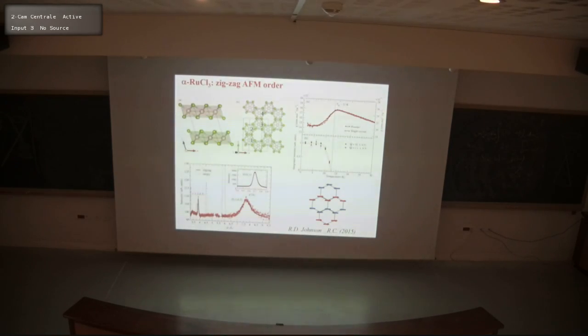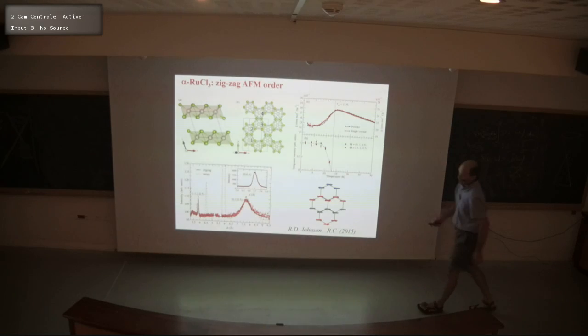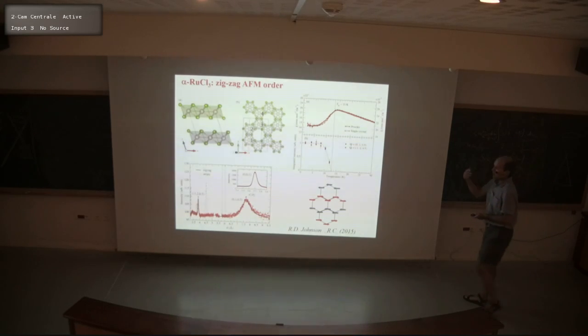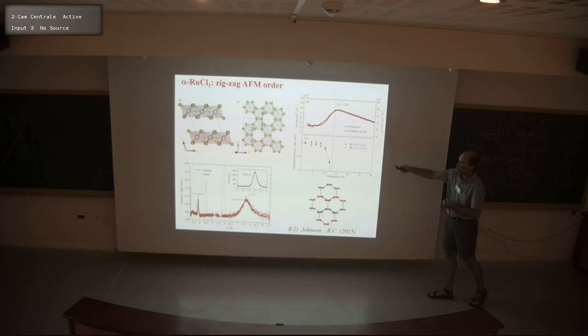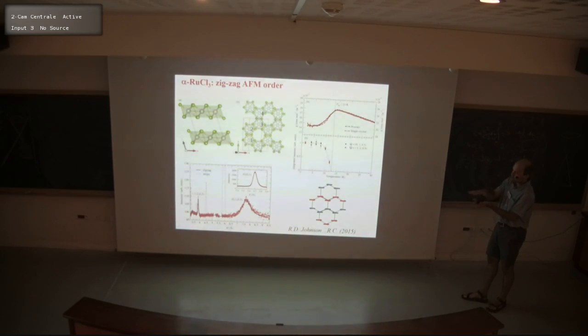So briefly about ruthenium chloride. So this has the same crystal structure at high temperatures as the two materials that I've described. So honeycomb layers stacked with an offset. And at low temperatures, it orders in a zigzag magnetic fashion, as one can find out from neutron diffraction measurements. And in samples that are very high purity, single crystals with no stacking faults, there's a further structural transition to a more high symmetry structure with sort of rhombohedral symmetry, but where still the in-plane structure is zigzag, but more complex pattern in between the layers.